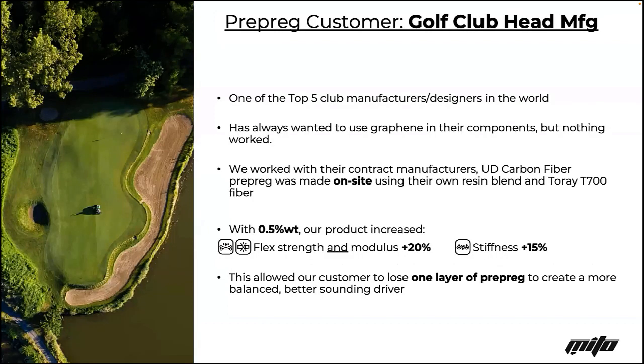Another use case, this prepreg customer, is a golf club head manufacturer. They're one of the top 5 club manufacturers in the world, and they've always wanted to use graphene, but nothing has really worked. They've tried and tried again, whether it's nanotubes or graphene oxide, and nothing's really gotten to stick. So we worked with their contract manufacturers. We made a unidirectional carbon fiber prepreg that was made on site. They took the powder, put it into the resin, put it through their hot melt system, and made prepreg with some Toray T700 fiber.